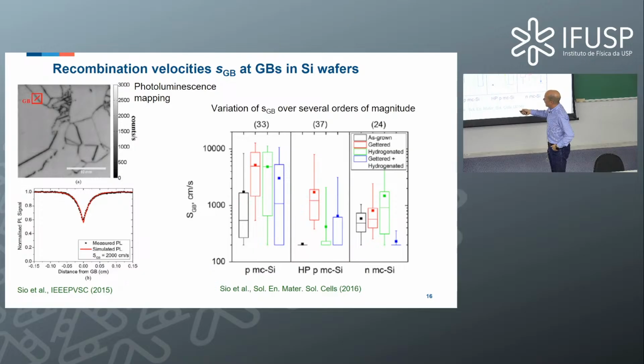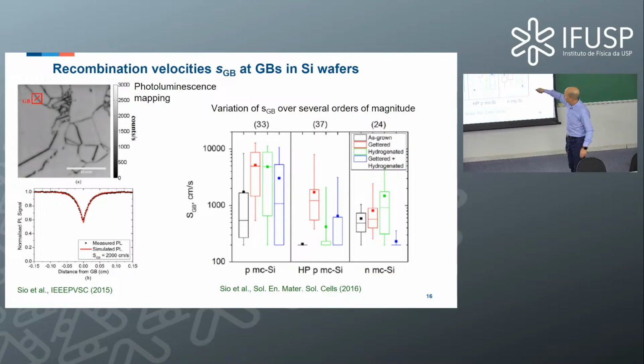And they are able to simulate the profiles. When you extract them, they exhibit a certain decrease, right? And they are able to simulate it by simulating the PL intensity and the corresponding recombination mechanisms. And if they plot these recombination velocities, you can see that the values they measure go across various orders of magnitude, from some 100 to some 10,000. And this is consistent for various types of wafers, P-type wafers, but also N-type wafers, and also various treatments. Okay? So this is actually a starting point for me.